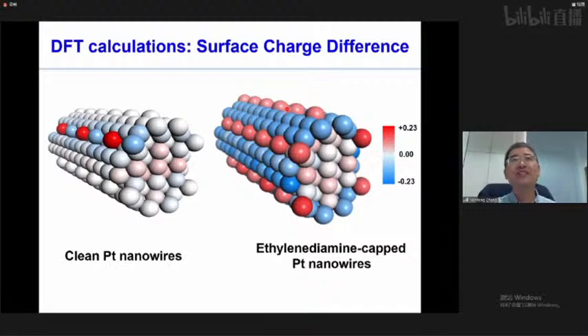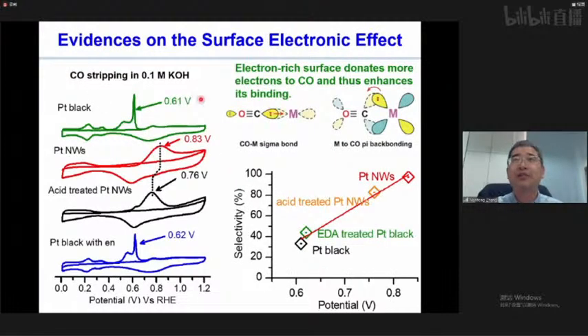Okay, so with this DFT calculation result, we then tried to use carbon monoxide as a probe. You see, if the surface is electron rich, which means we have more electrons that can back donate to the anti-bonding orbital of carbon monoxide, right? So in this, our CO stripping experiment suggests that with the bonding of the ethylenediamine, we do see much enhanced CO binding on the surface. And the enhanced binding strength is also proved by our FTIR measurements, because the wave number of the carbon monoxide vibration has been changed.